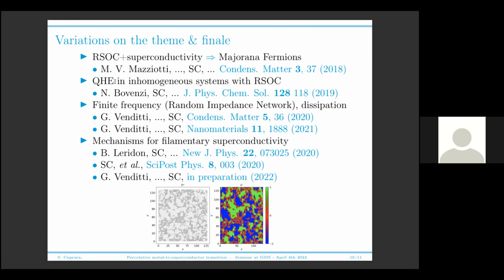We have studied, as I told you, we have gone even further in studying the finite frequency response with a random impedance network. Now we are even able to introduce dissipation in the superconductor, so to go beyond this approximation. In this approximation, if you are in the superconductor, you have a purely inductive response, no dissipation. We can introduce dissipation, which is a frequency dependence of the inductance with an imaginary part of the inductance that gives the finite frequency dissipative response inside the superconducting cluster.